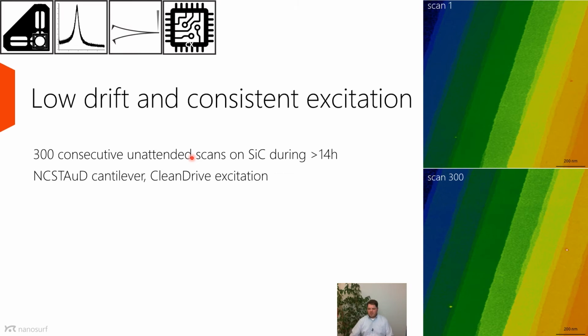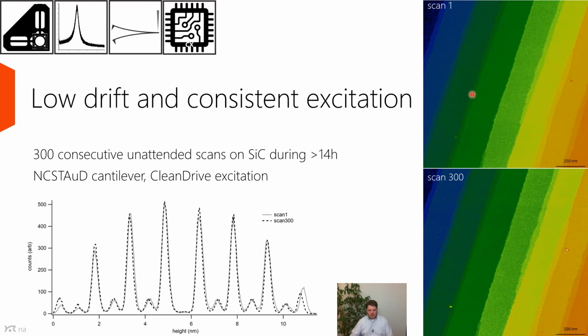So that means you can identify there's some small defect over here, which is also here. So there's almost no drift in these measurements, and also the step height is unchanged. We have more or less the same height distribution compared to the first scan when we look at the 300th scan. And another indicator is that we can measure the roughness, for example, on this terrace here or on this terrace, and they are basically identical. So it means we have hardly any tip wear, which is also important for stable scanning, so that you do not blunten your tip, so that you can image gently but reliably over a long period of time.